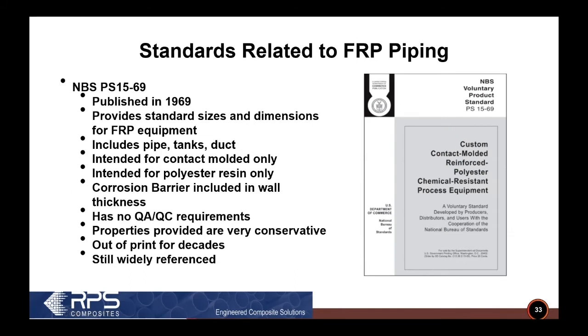When it comes to standards, there's a lot of standards out there, but until recently, there actually hasn't been one good standard for FRP piping. There has been a standard kicking around since 1969 called PS 15-69. It was intended for polyester resin and contact molding, so it wasn't made for filament winding. And the corrosion barrier is included in the wall thickness calculations in the spec, which is generally not recommended nowadays. And the properties used in the spec are very conservative. It's still widely referenced, although it's been out of print for decades.